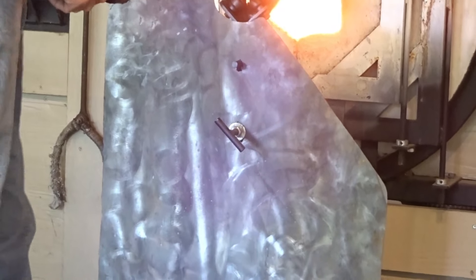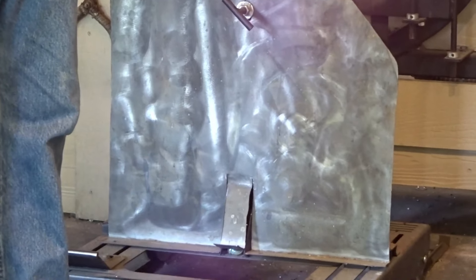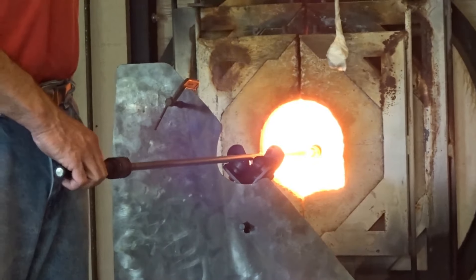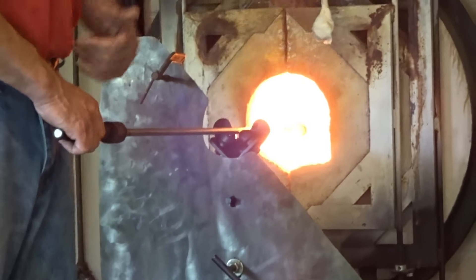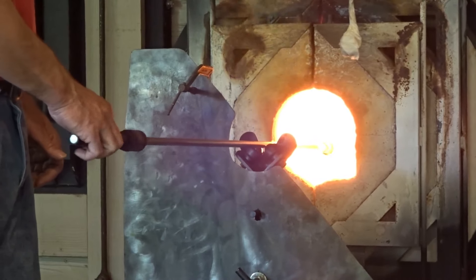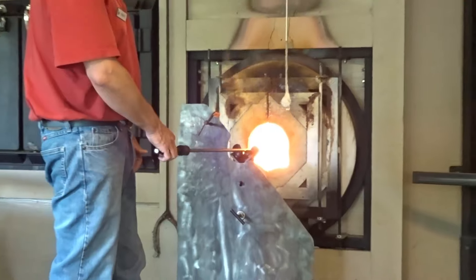What's all the color made out of? Well, it's all glass. To get colored glass, you add metal to clear glass. In the case of this color, which is called dark gold pink, it's got gold. You add enough gold to it, it will turn into pink. You add more gold, it turns into darker. Violet also has gold in it. Sometimes it has a little copper or cobalt to turn bluish violet.